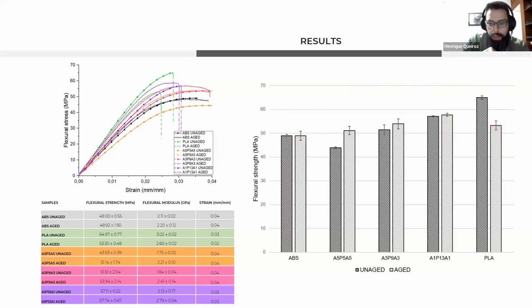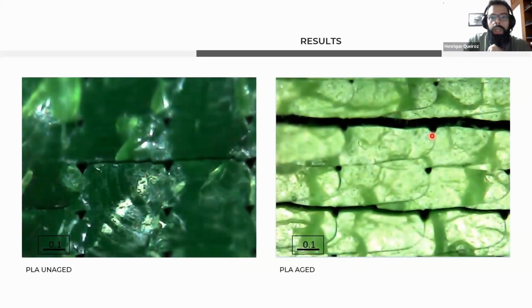Let's see here. So now to talk a little bit about the fracture of the specimens. So over here, we have two representative failure modes. These are tensile specimens, right? And you can see this is the unaged PLA. And we see, of course, the voids of the printing deposition, which of course are always going to be there. And we also have some small imperfections between the deposition of the layers, right? This is expected. No specimen is printed perfectly.